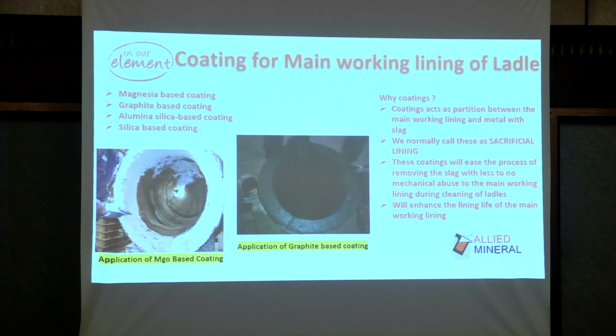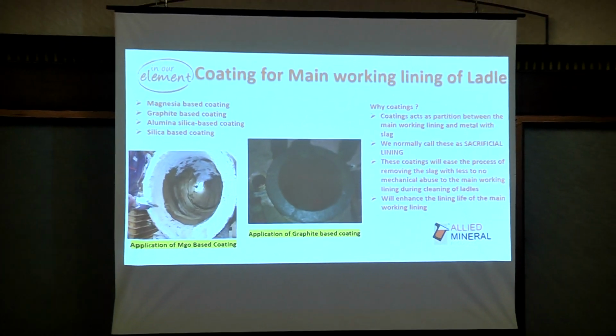T-coat, for example, is insulating. It's got 3 different types of fibers in it, highly insulating. So if you're using a cover on your ladle, you can reduce the heat loss drastically in your ladle by using a coating of T-coat. It's kind of like cold board technology in a bag, except with cold board you have to go with one thickness. You can't change it. With T-coat, if you are happy at 10 millimeter, you can put 10 millimeter. If you need 20 millimeter, you can put 20. You can do whatever you want. You can put it thicker in different zones than others. So it's very flexible that way.